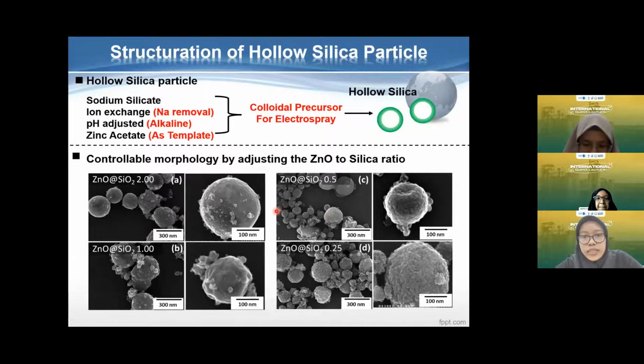You can see here, if we add the amount or increase the concentration of the silica particles, the zinc oxide particles are more covered by the silica particles. And then if we increase again the amount of the silica particles, all of the surface of the zinc oxide particles can be perfectly covered by the silica particles. And then the last here, there is a small size of particle. This is the silica particles, and now we cannot see the zinc oxide particle because its surface is already perfectly covered by the silica particles.